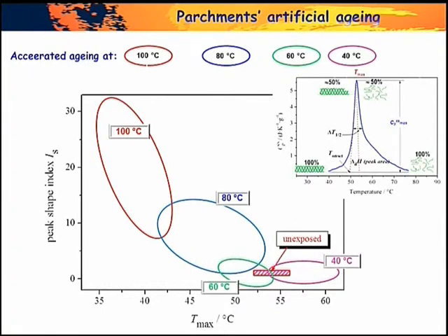So, if we consider the peak parameters, which are maximum temperature, height of the peak, and half width of the peak, and plot all the samples treated at 100 degrees, 80 degrees, 60, and 40, independently of the relative humidity, we've observed that samples group. So all samples aged, for example, at 80 degrees Celsius fall in this area, and so on. This small dashed rectangle is the area where unexposed parchment fall.